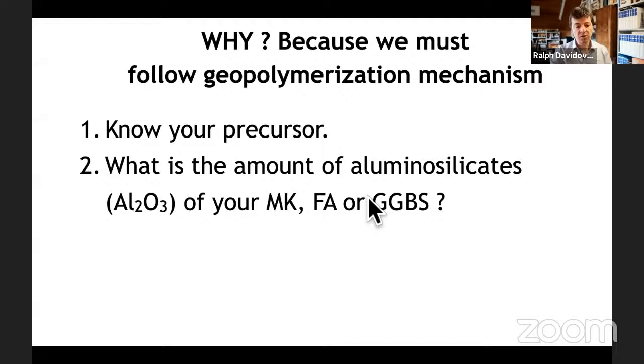What is the amount of aluminosilicates, Al2O3, in your metakaolin, fly ash, and slag? You must know the chemical and mineralogical composition of all your materials. You must test and choose them for their reactivity. Don't use materials that are not reactive. For example, take only class F fly ash with no lime CaO in it.